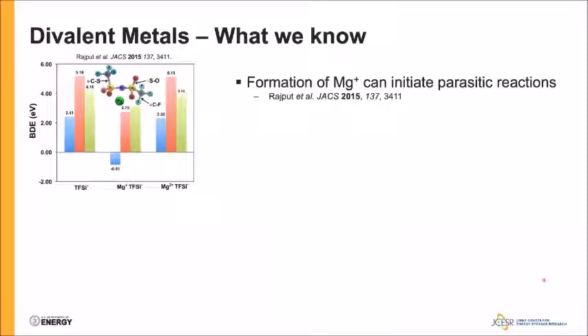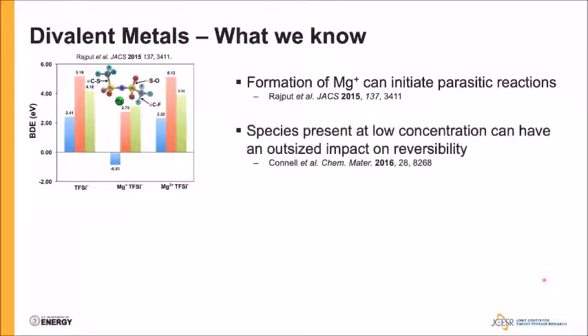I'll highlight a few points relevant to what I'm going to speak about today. The first is that there's some really strong evidence that as we move to reductive potentials, the formation of any kind of monovalent species in these electrolytes can lead to some interesting chemistries, in particular parasitic reactions that lead to decomposition of the anionic species in your electrolytes. In addition, it's been shown that species present at very low concentrations, even ppm levels, can have a really outsized impact on reversibility. So we need to pay attention to not only the majority species in the electrolyte, but also things that may be present even at minority concentrations.